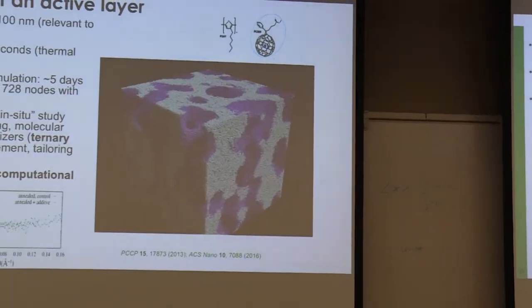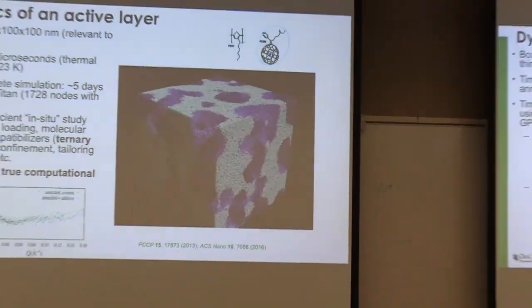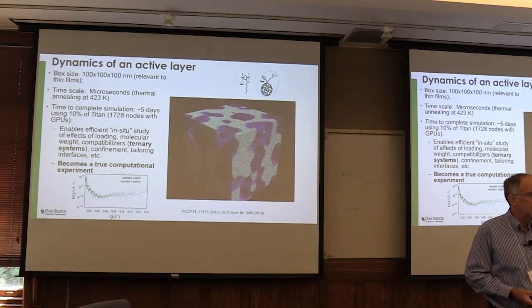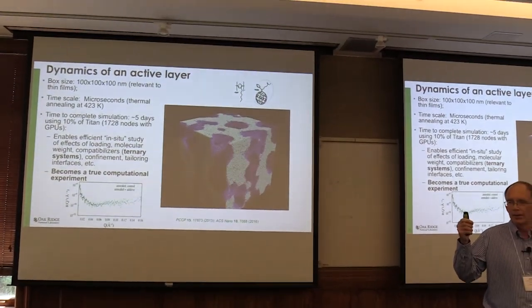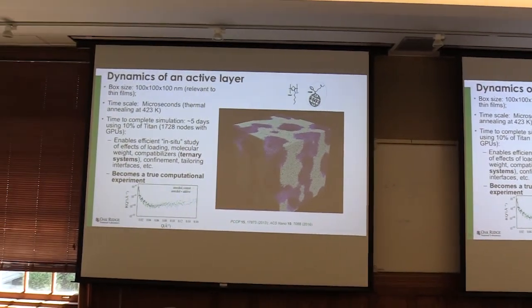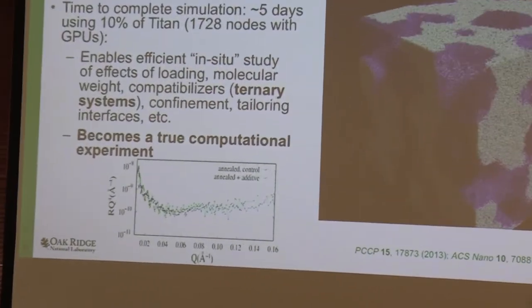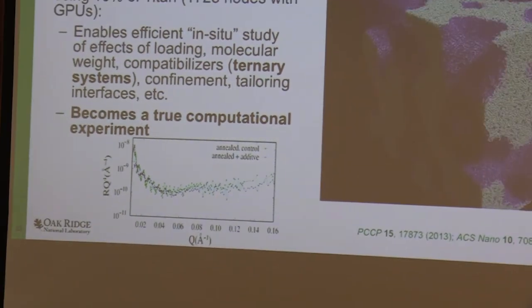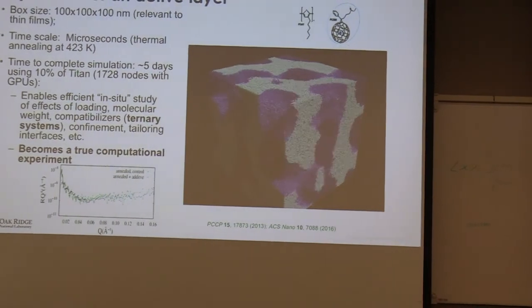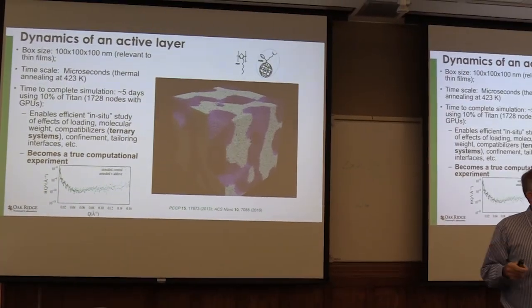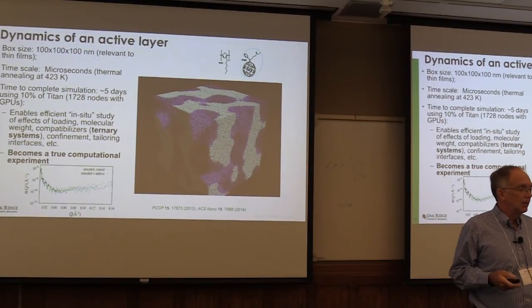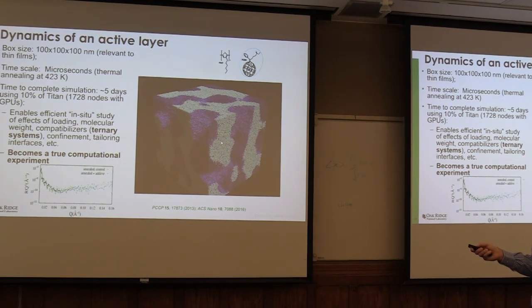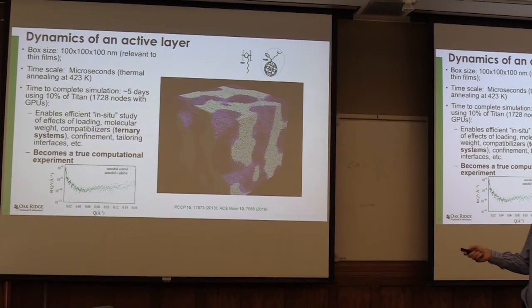And what we know is if you put a photon into a semiconductor material, you form a bound electron and a hole. That's called an exciton. And that thing will recombine and just give you heat or eject a photon. But if you can separate that electron from that hole, you get electricity. And that exciton will travel about 10 nanometers. So you can see there's some bad spots here that are bigger than 10 nanometers.